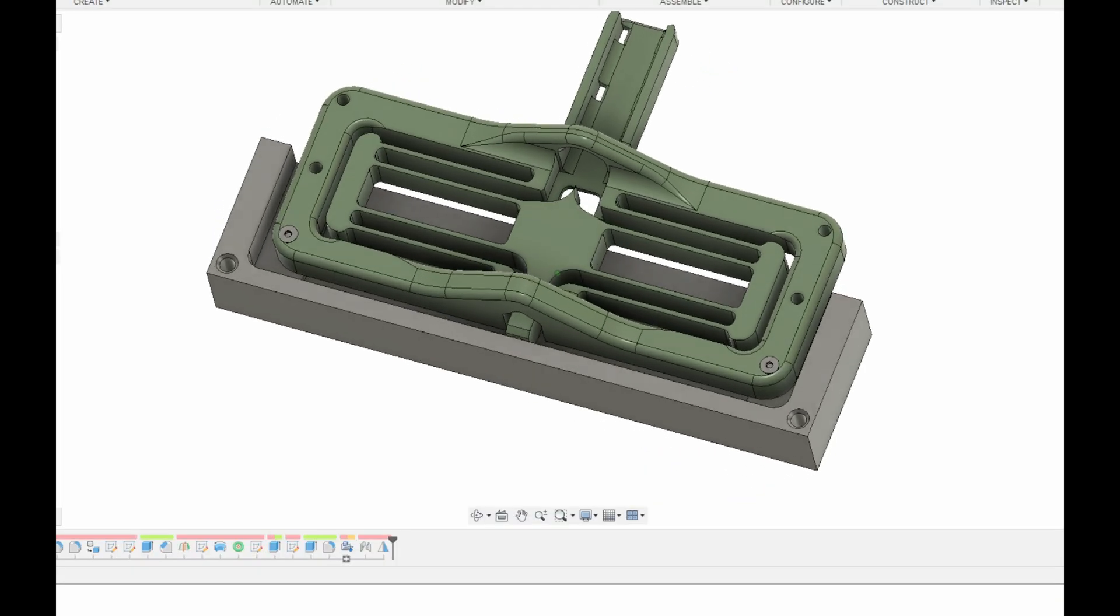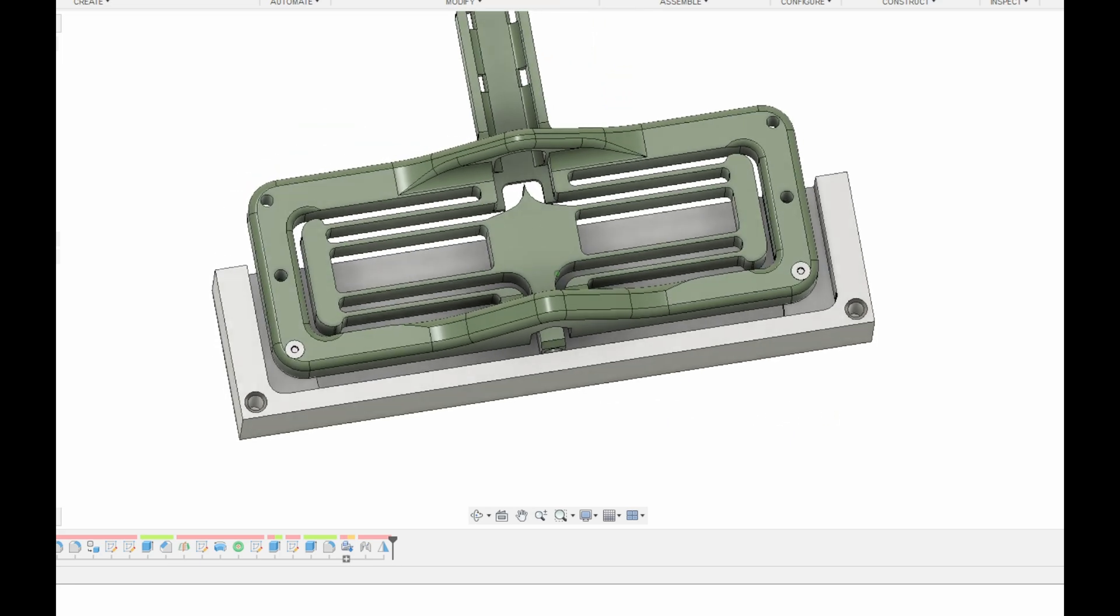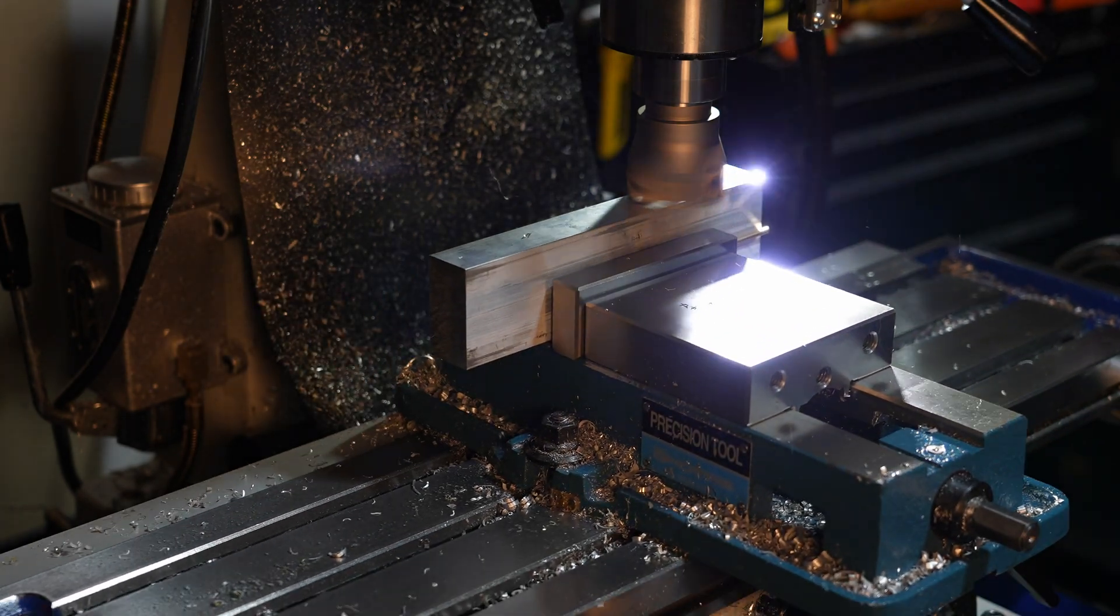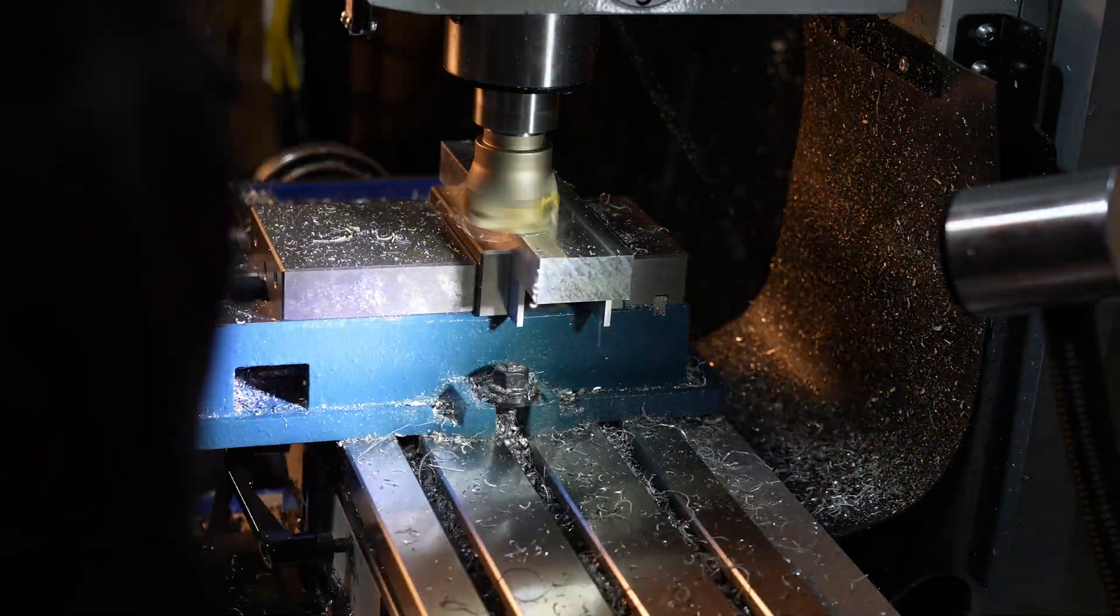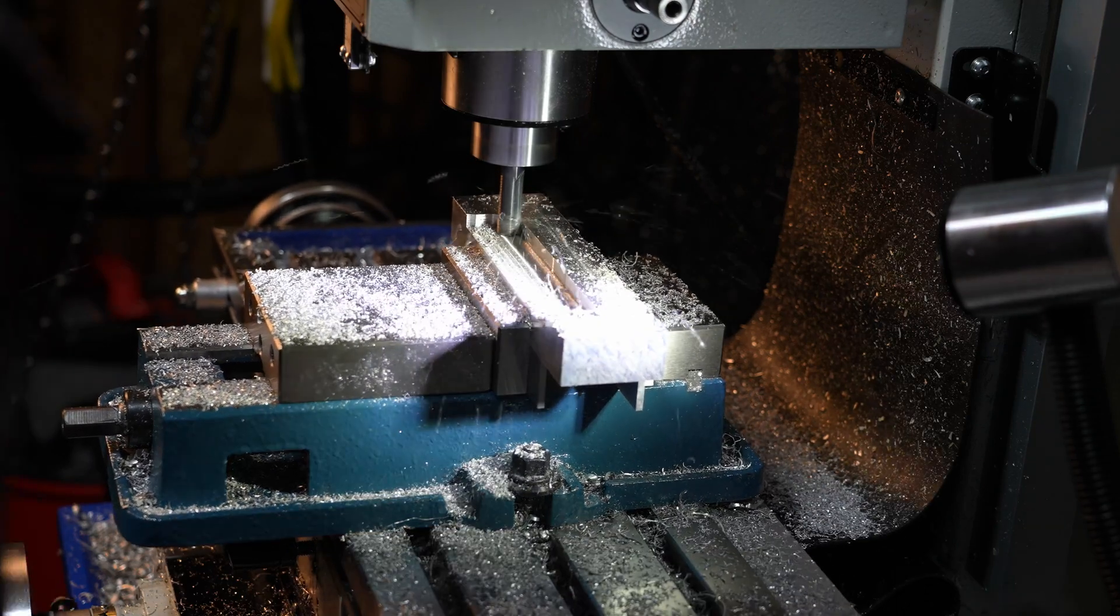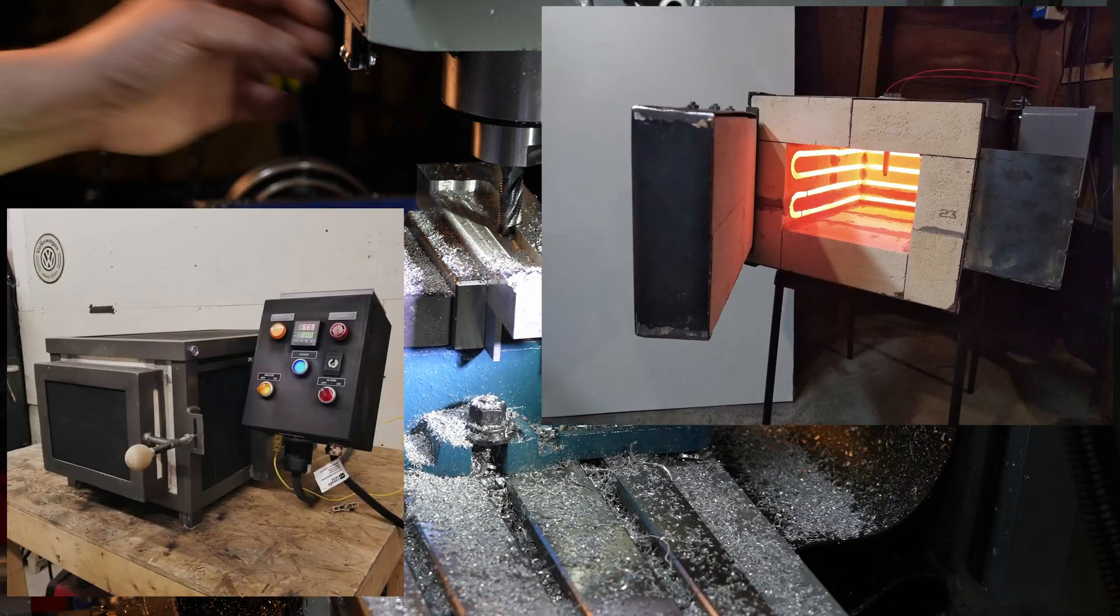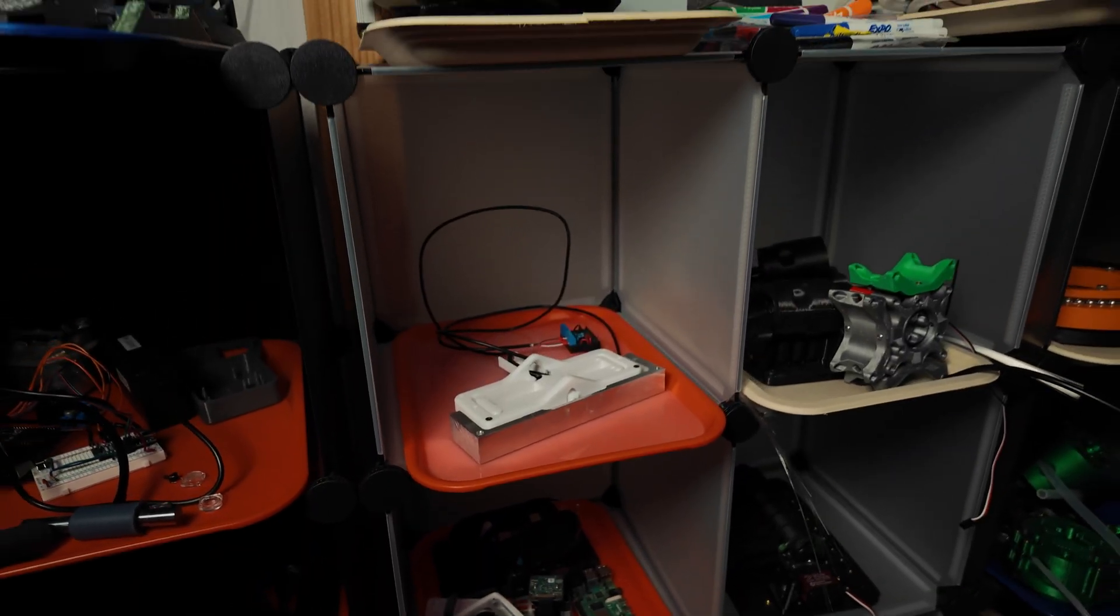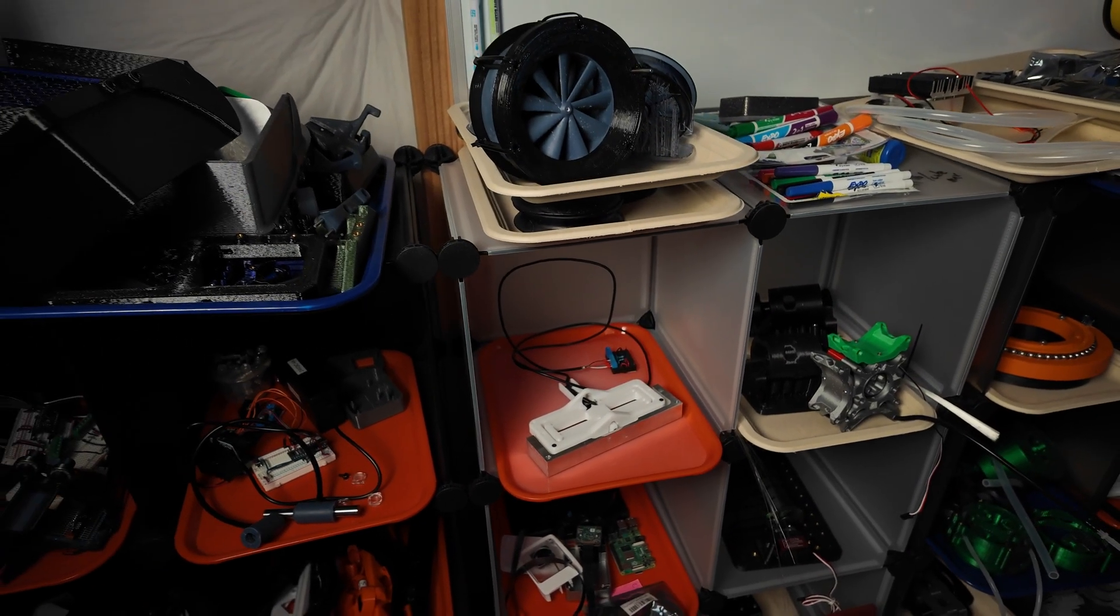For this one, I also added a couple of blind holes to embed some temp sensors close to the action. In my experience, it's preferable to try and keep the null block made from a single piece of material to avoid any extra uncertainties caused by creep or other movements at joints. For this same reason, if you really want the decimal points, it's also a good idea to anneal the part after machining to keep the residual stresses from creeping on you. Or, you can go my route and get sidetracked for a couple of months after machining it. Hopefully it's all relaxed by now.